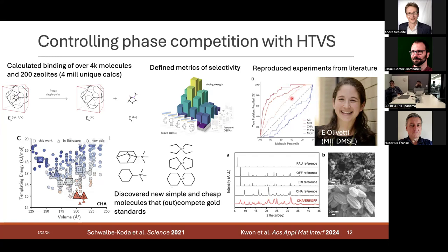Folks typically report what precursor, what temperature, for how long, right? The variables to track are easier than in other domains, and folks report negatives too. So they extracted a few thousand recipes. So we were able to match the recall between our calculation on the X, right? This is how our calculations would rank a molecule. And this is the likelihood that it has appeared in the literature, right?